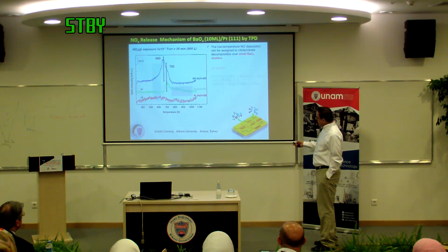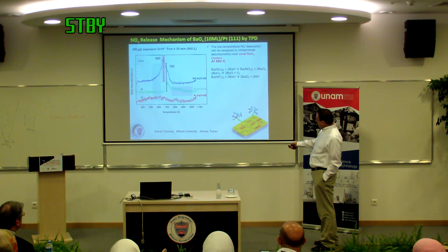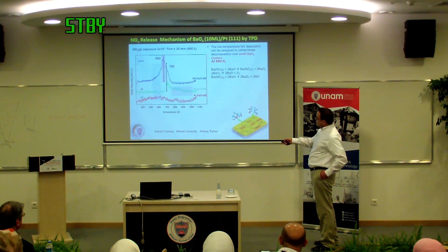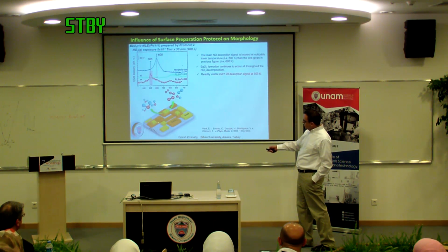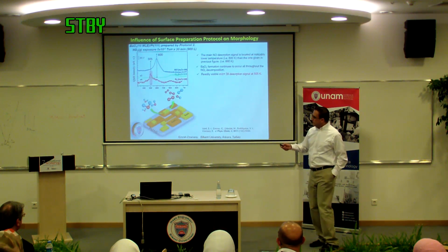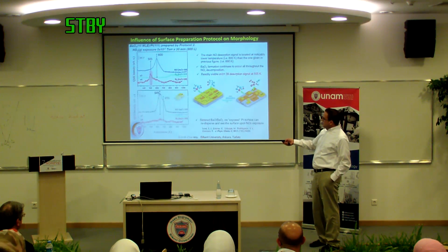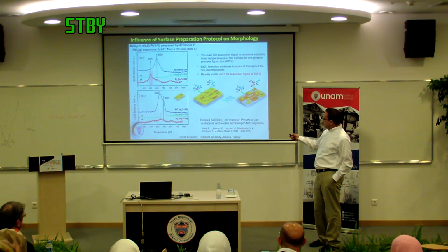It turns out that if you design the catalyst, in which case you block the platinum, you deactivate the platinum, you get a certain desorption. And if you have a different catalyst where platinum is exposed, in other words, you get heterojunctions or interface between platinum and barium oxide, you get a different chemistry, you get direct NOx reduction. So you can form nitrogen. So the chemistry is different. What's interesting is that those two different surfaces are regeneratable. I can switch between those two surfaces by either dosing NOx or heating in oxygen.